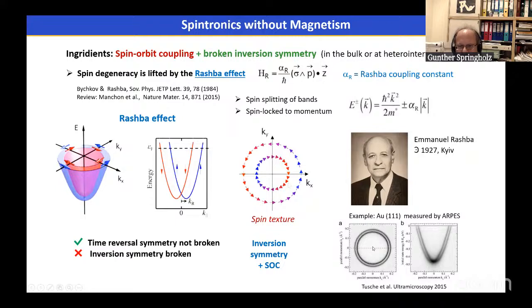Here on the lower right-hand side, there's an example of actual measurements of the gold 111 surface using photoemission spectroscopy, where one exactly sees this Rashba splitting of the surface state of gold 111 due to the symmetry breaking caused by the existence of the surface.